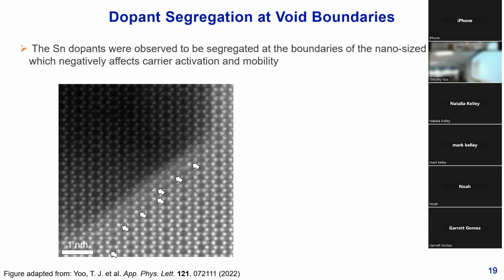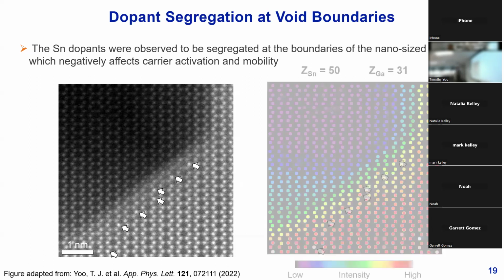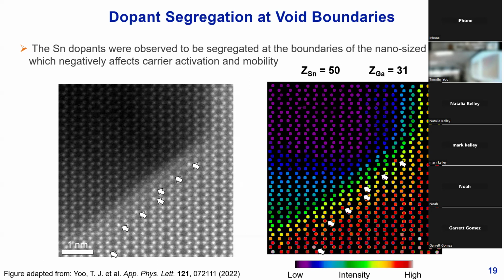What we do see upon a closer look is that there are certain atomic columns near the border of these voids, marked by the white arrows here, that appear to be somewhat brighter than their neighboring atomic columns. And so in order to more quantitatively determine whether this is really the case or not, and get a little bit better contrast of this area, we can apply digital image processing to capture the precise intensities of each atomic column after fitting their positions.